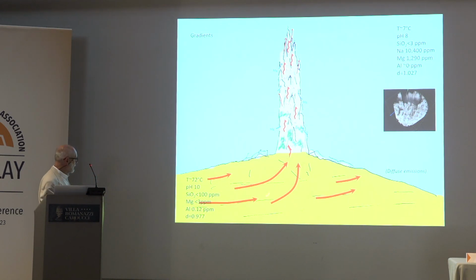So it's the hot fluid that emerges from the bottom, and in contact with the seawater starts to flow up, because it's 32 here and this is 7. The temperature modifies the density. This is the density of the seawater at this temperature, 1.027, but for the hydrothermal fluid it is 0.977. So it's a buoyancy effect. And in the path going up, it interacts with the seawater, producing the precipitation of the silicates.